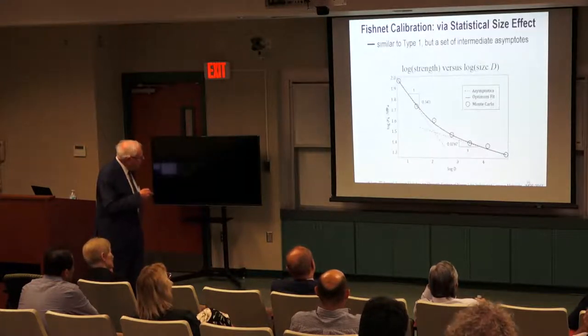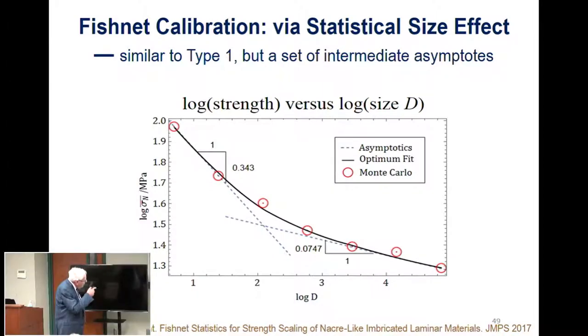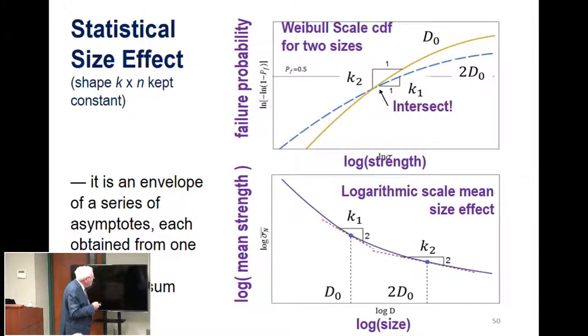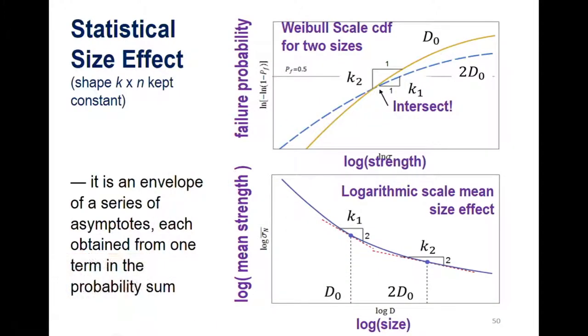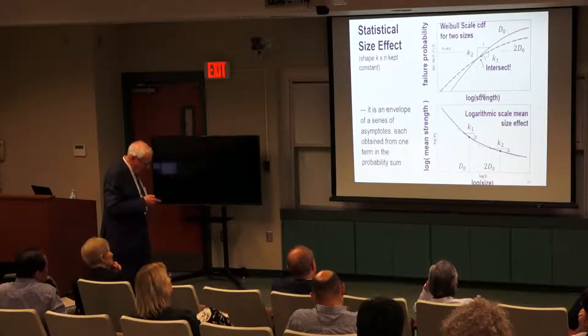Now this is a size effect that we compute. It's similar to the type I showed at the beginning, but somewhat different. For brittle fishnet, it's actually a curve which is an envelope of asymptotes which correspond to one link, two links, and so forth having failed before maximum load. What is interesting is that as you change the size, the distributions change, or rotate about one point here, generally. And this corresponds in the size effect curve to transitions from one asymptote to the other.